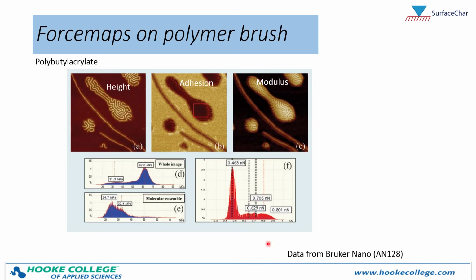And the final example is a force map collected on a polybutyl acrylate brush. Here's a pretty high resolution force map showing the height, the adhesion, and the modulus, where the adhesion and modulus were extracted from these individual force curves collected at every pixel. Then we can do histograms on the adhesion plot shown here, and we can see the different components, mapping them out by the adhesion in the material. Same with the modulus. We can get a histogram of all the moduli values and then focus in on just the molecular ensembles or try and tease out some of the different components of this brush.